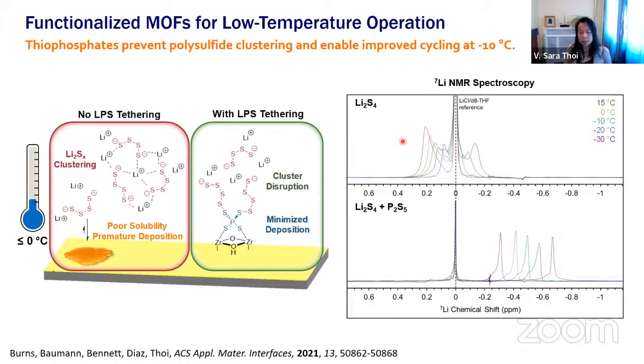Another way to look at this is that we took solution lithium NMR spectroscopy. We wanted to see how the thiophosphate in general disrupts polysulfide clustering. So on top here, you see a solution of polysulfides in equilibrium. And you'll see here that as we drop the temperature, the single peak of lithium starts to shift to the right, but also starts to diverge. And you can see multiple peaks here at lower temperatures. That to us indicates that there's some clustering that's occurring that leads to these different identities of lithium ions.